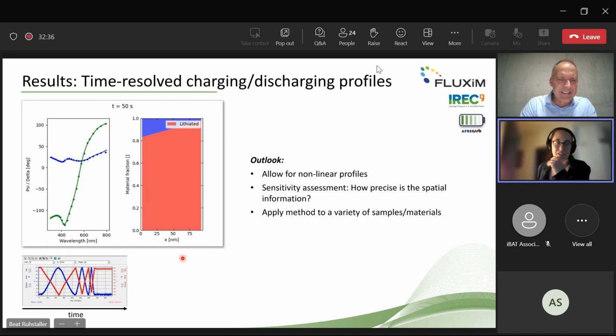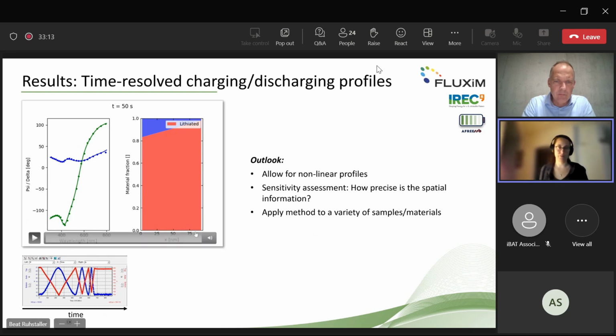But in principle, you can just see that the profile changes over time, the composition, and also slightly the slope changes. So what we want to do next is to allow for nonlinear profiles. Up to now, it was really limited to this linear, maybe not so realistic, profile, and then also look at the sensitivity, like how precise the spatial information is that we can obtain from this method. And then, of course, we're ready to try it for different samples, materials, different charging currents, and so on.